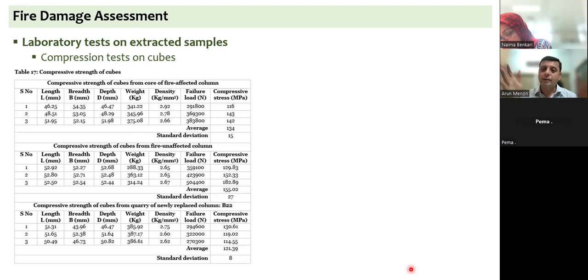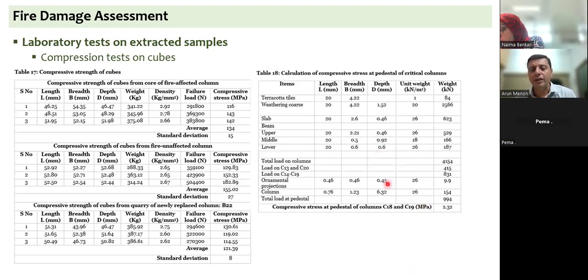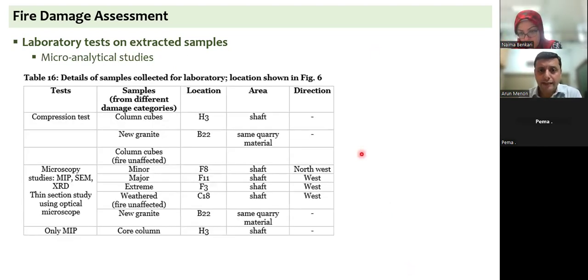But then the outer layer, as I was mentioning, was flaking. And so we had to be careful that the section of the columns was reducing, and you could have buckling of these columns. So that point in mind, the compressive strength of the columns was really not compromised. So this is something that we were able to look at. We then, as I said, for the microanalytical studies, collected samples from different locations in the columns. And we looked at columns that are affected, not affected at all, columns that are affected in a minor way, major way, extreme way. And I was mentioning some of the columns were already weathered before the fire. So we took some samples from that. We took some samples of new granite as well, so that we are able to compare the microscopic condition of the samples.